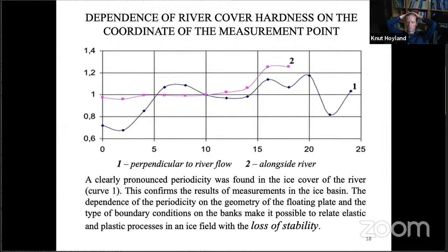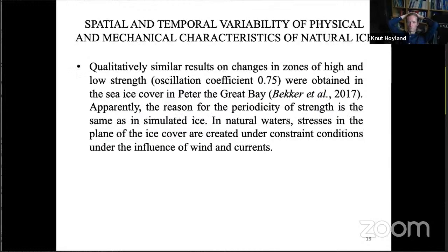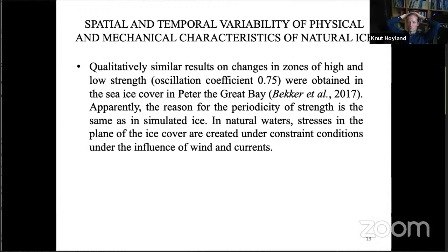Now authors would like to switch to the river basin measurement data as presented on this slide. Here one could see differences in hardness along and across, perpendicular to the river flow. There is a potential relation between elastic and plastic processes and the loss of stability. The phenomenon of periodicity of strength has been previously observed in the Bekker with co-authors paper of 2017, as mentioned. It is likely that the cause for sea ice is similar to the tested simulated ice.